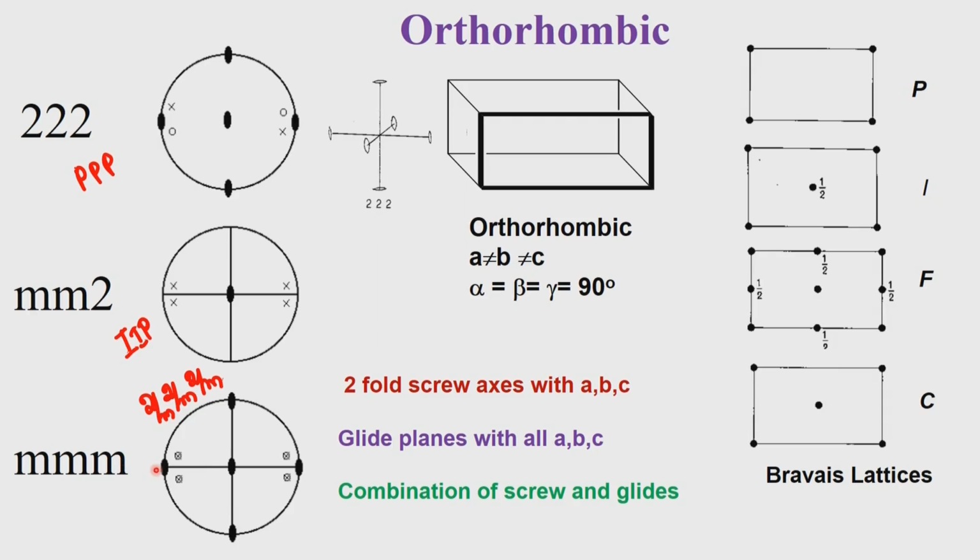PMCA is MMM point group symmetry, which means it corresponds to 2 by M, 2 by M, 2 by M. And when we say PMCA, it will be 2 by M, 2 by C and 2 by A. So, the glide planes will always invoke the presence of 2 2 2. That is why the minimum symmetry you should have in an orthorhombic system is 2 2 2. Unless you have three two-fold axes intersecting with each other, in general you will not be able to generate orthorhombic systems. And so, those are the restrictions, all right, but the flexibility is immense.